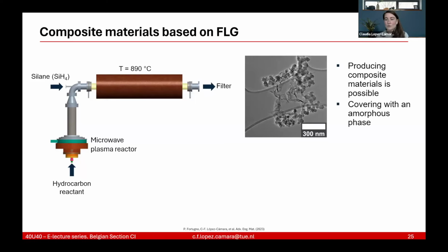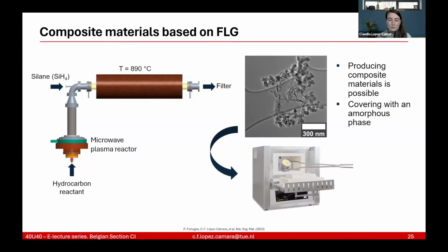The idea was producing composite materials to see if it was possible, and covering them in an amorphous phase. At the end of the day, in the filter, we were seeing this kind of graphene, this very crumbled sheet, and then these small particles around, which were silica. However, we said, okay, let's see what happens when we anneal it. Basically, what happens when we put it in the oven overnight.